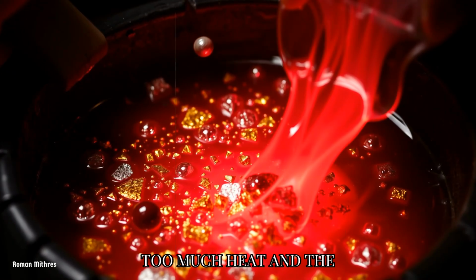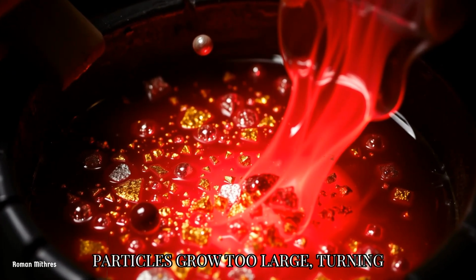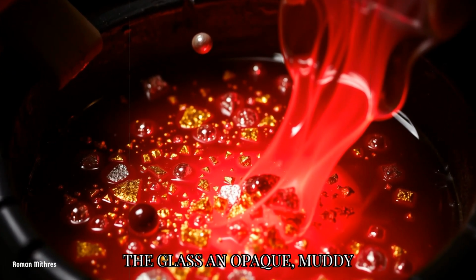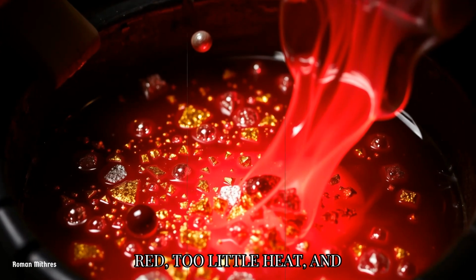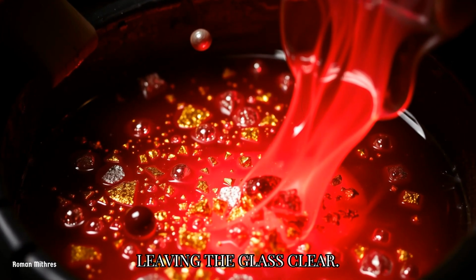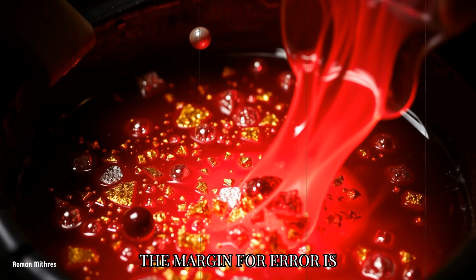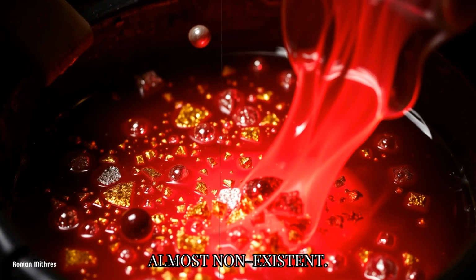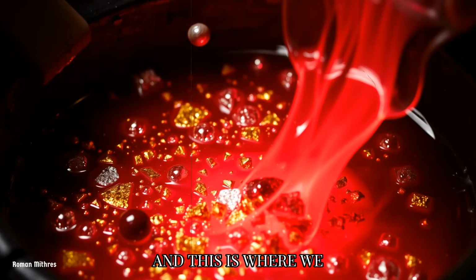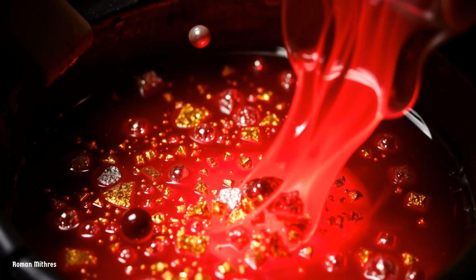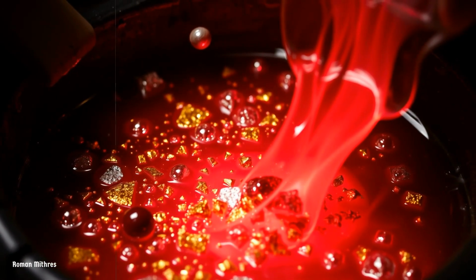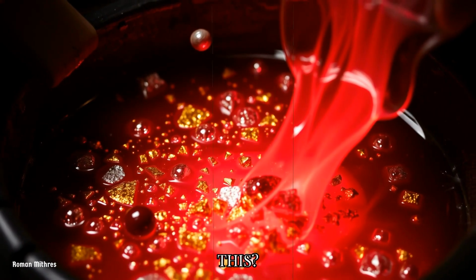Too much heat and the particles grow too large, turning the glass an opaque, muddy red. Too little heat, and they don't form at all, leaving the glass clear. The margin for error is almost non-existent, and this is where we arrive at the deepest, most compelling mystery of all. How did they possibly discover this?